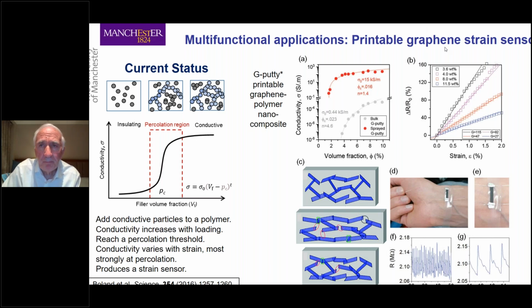Now, when you deform the material, you find that the resistance increases, and the resistance increases pretty well linearly with strain. So now we have the essence of a strain sensor. But if you look at these curves here, the top curve is for the lowest loading, 3.6%, just at the percolation threshold. And that gives a very high level of sensitivity, which we call a gauge factor, and allows us to measure strain in great detail and great precision, a very high gauge factor.